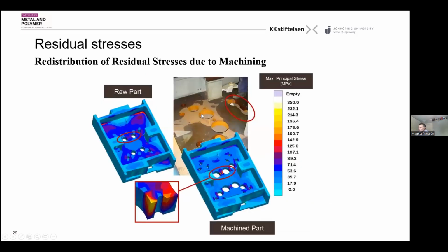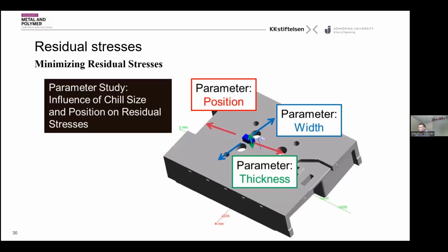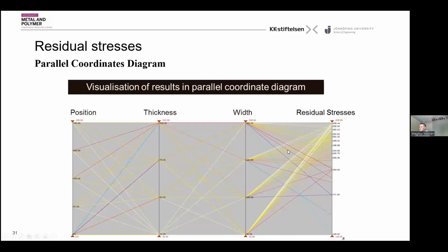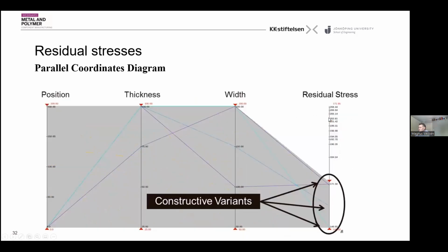So what was done was they tried to cool the part in this problematic area by introducing chills. And that was done in this way. They made a chill so they take away more heat during cooling, and they could vary the thickness of the chill, the width of the chill, but also the position, so that you can move it around to different locations. I don't know in detail how that was done, but you have the position here, you have the thickness, the width, and you have the stresses.